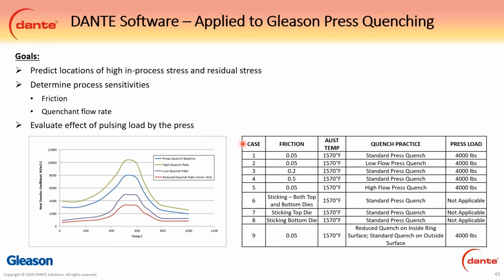All this was simulation. We used standard press quenching to evaluate a few different friction coefficients, 0.5, 0.2, 0.05. Then used our 0.05 friction to evaluate a few different flow rates. We then looked at what happens if the top and bottom dies stick, and what happens if the top die sticks by itself or the bottom die sticks by itself. So the sticking essentially shows the no pulsing, because if you keep pressure on the part, you're likely to hold it into place, which would essentially be a sticking situation. So the part refuses to move. As you thermally contract it, it does not contract. As you expand a martensite, it does not expand, at least on the surfaces in contact with the die.